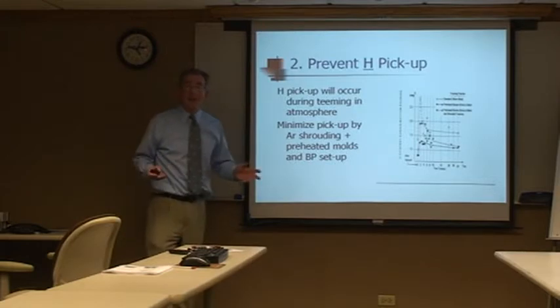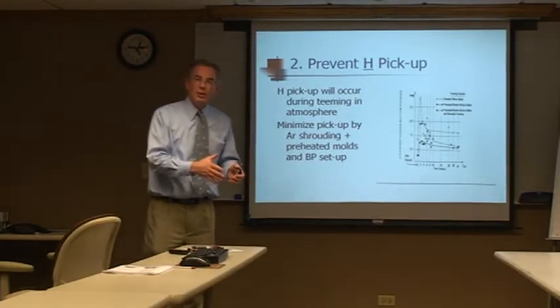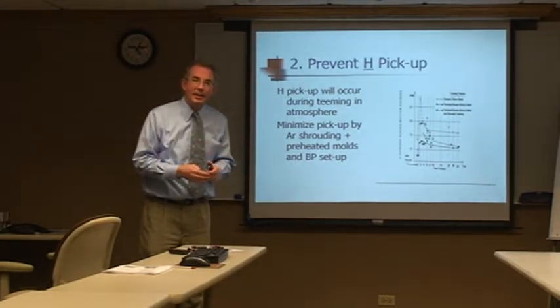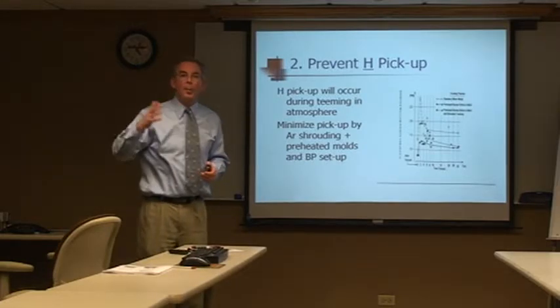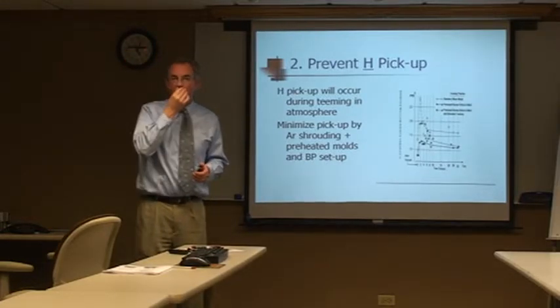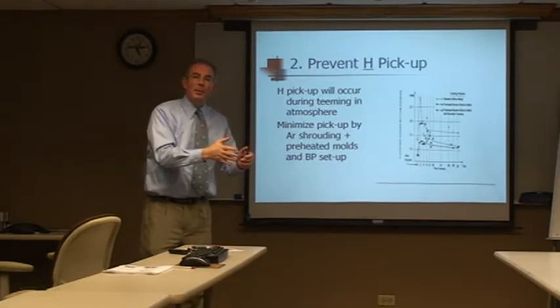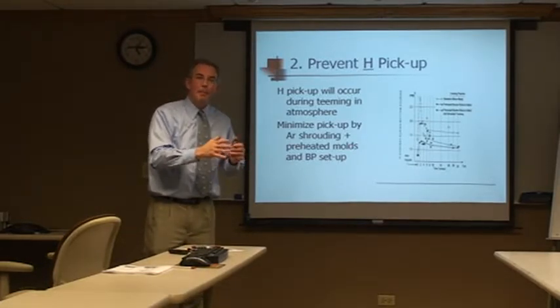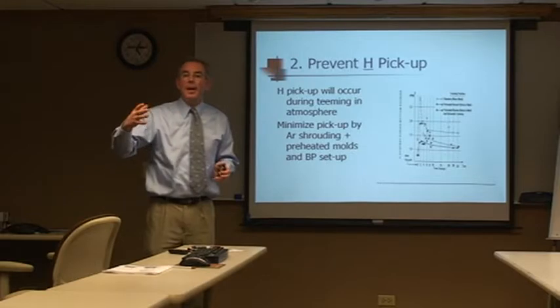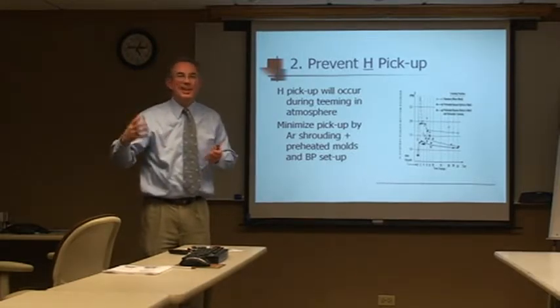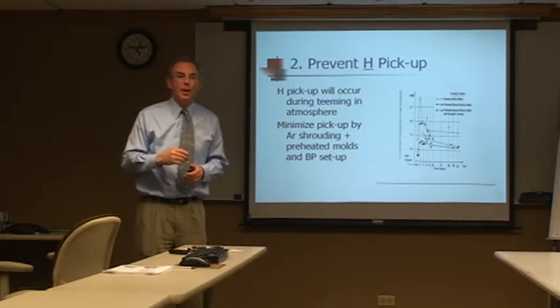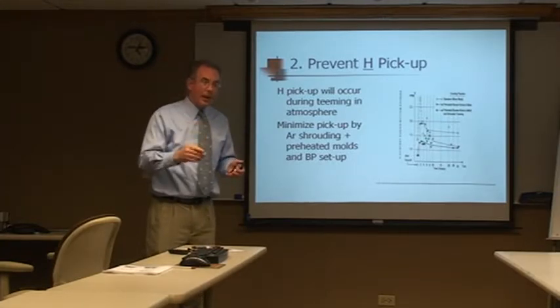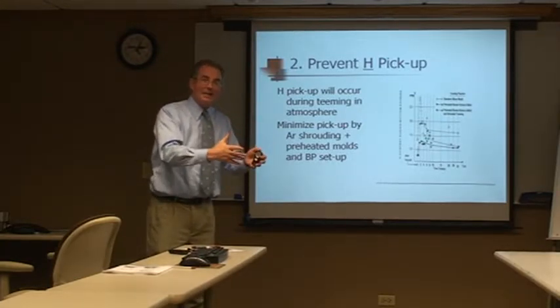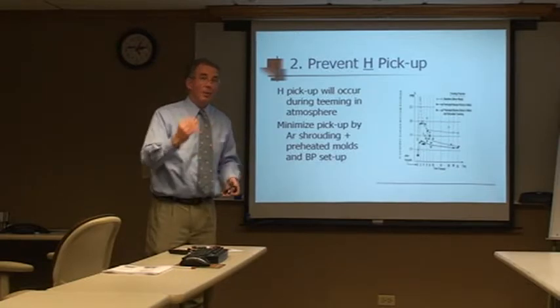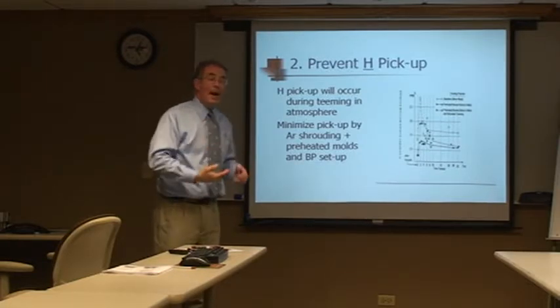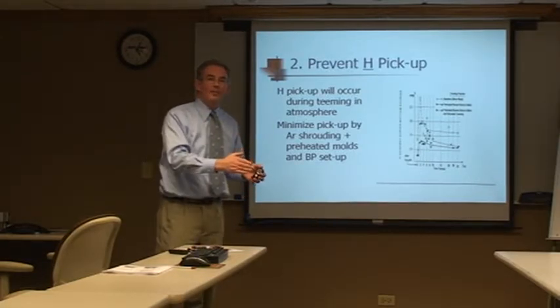One of the other things is measurement. We measure the hydrogen after vacuum degassing in process. So if we're working to a 2.0 part per million specification from Scott Forge, after vacuum degassing, we work to 1.5 maximum because we know that we will pick up hydrogen in the atmosphere, statistically about 1/2 part per million. So at the end of a good degassing cycle, we'll take our hydrogen sample. If it's 1.6 or 1.7, we go back and re-degas until it's 1.5.